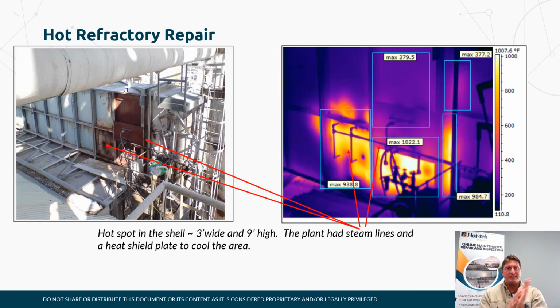So here we can see in the refractory case study some serious carburized steel up top. When we take an external IR of the heater, we're seeing temperatures above 1,000 degrees. We can repair these when we see very high skin temperatures, like over 1,000, if we have those limits there. We can also repair on the structural beams when we're seeing the heat get past the refractory protecting that structural beam, in the radiant section especially, and being on site, we can repair those areas.